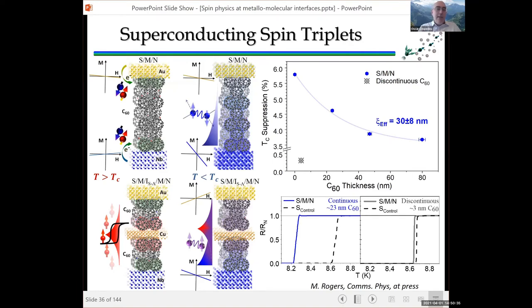So the Cooper pairs from the niobium are going to diffuse into the C60. We can measure this diffusion by measuring the superconducting critical temperature suppression when we put C60 and gold on top of the superconductor. And what we observe is that the Cooper pairs diffuse with a typical length scale of the order of 30 nanometers. So your Cooper pairs will diffuse into the C60 for about, on average, 30 nanometers. Now, if we have a copper C60 interface, what we expect to see is that the induced magnetization at this interface will affect the diffusion of the Cooper pairs. And indeed, that is what happens.